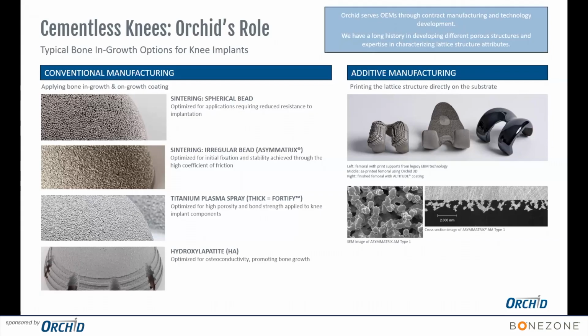Now, the additional trend that we have seen recently, and we get a lot of interest in this, is the fact that there is a move to moving away from cobalt chrome and using titanium as a material even for knee femoral components, because it is generally believed to be more biocompatible. Patients are less likely to be sensitive to elements in titanium than they would be to cobalt chrome. So issues like allergies and things like that are either completely eliminated or reduced to a great extent if you were to make it out of titanium.